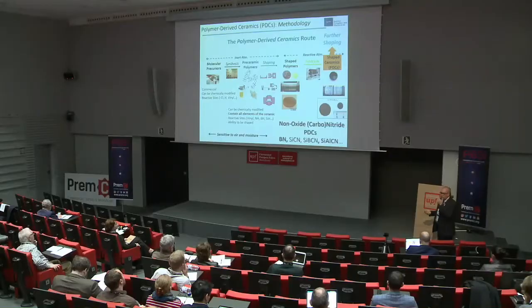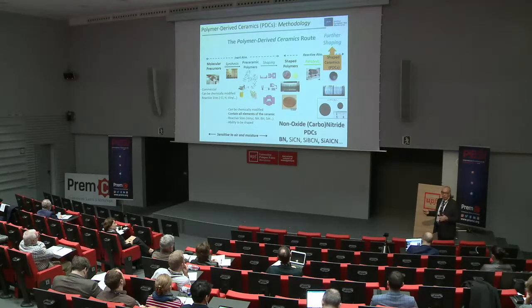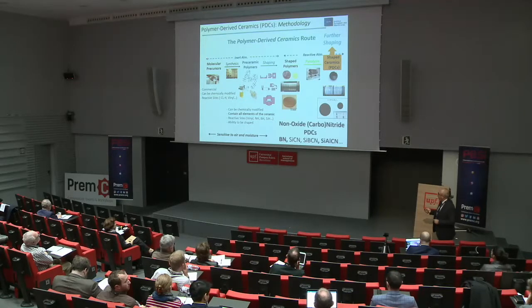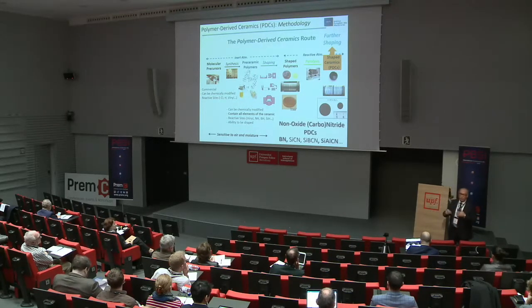And the difficulty with this method is that you don't want to have any oxygen in this ceramic, and all of these precursors are sensitive to air and moisture. So starting from room temperature to around 1,000 degrees, you have to work in a completely neutral atmosphere, for example nitrogen or argon. Also, you have to keep in mind that from 0 degrees Celsius, you have to go at the end to 2,000 degrees for the complete transformation into the ceramic.